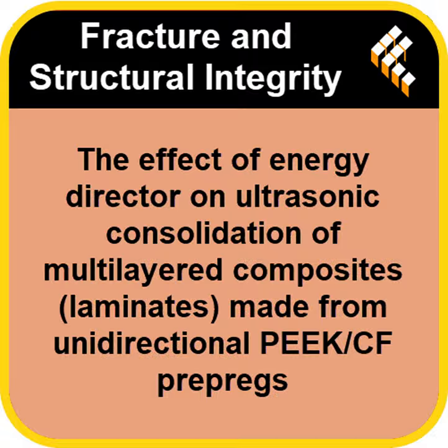So longer time equals stronger bond. That sounds like a clear winner. 60 MPa is an excellent number. It sounds great. Until you look at the ED results. Uh-oh. Their ILSS peaked much earlier and much lower. It hit about 40 MPa at 800 milliseconds. But here's the kicker. When they pushed the time to 1200 milliseconds, the ILSS crashed. It went down. It crashed down to about 30 MPa.